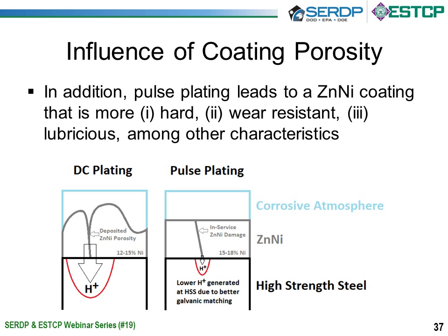In addition, one of the reasons that might have influenced the re-embrittlement was the influence of the coating porosity. With the DC plating, you have these pores, so you have these potential pathways of solution down to the substrate. During the corrosion process, hydrogen is evolved and it can be absorbed into the high strength steel. So in addition to maintaining the composition in the range such that the open circuit potential is close to that of steel, but still below, the absence of these big pores generally means that you're going to see less ingress of hydrogen to the surface, thereby providing better performance.